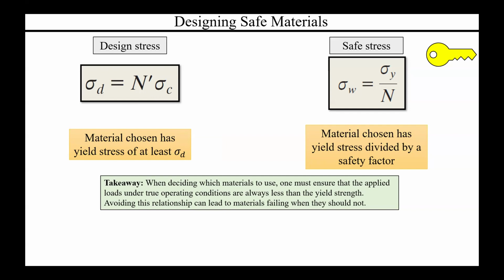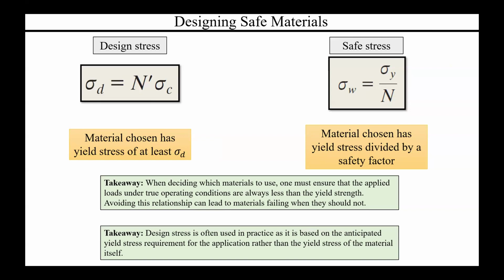So in principle, you would want that sigma y divided by your safety factor. So you would want materials that more or less have 5 times larger than whatever value you wanted. In principle, they effectively do similar things, but there are different reasons why you would use one versus the other. Design stress is often used in practice because it's based on the anticipated yield stress that you would need for the application rather than specifically the yield stress of the material itself. So this is an important distinction: if you already have the material in mind, maybe safe stress is a better way of doing it. But if you have more of a what I actually need in terms of a yield stress, then that sigma D of the design stress gives you a starting point to then go see what materials have, say, at least sigma D.